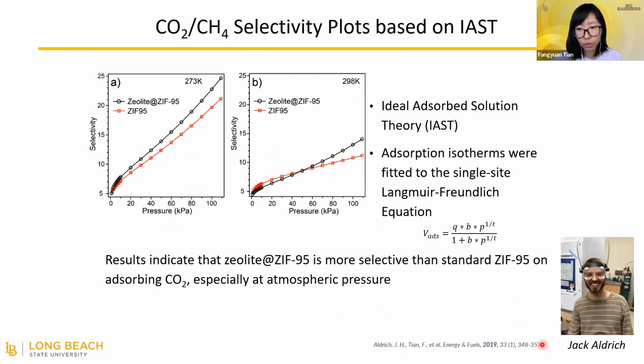Another student in my lab, Jack Aldrich, did the computational work based on the ideal adsorbed solution theory, or IAST, to figure out the selectivity of this material toward carbon dioxide and methane. And we noticed that for the hybrid material, even at room temperature, the selectivity can go up to around 16. That means for every 16 molecules of carbon dioxide trapped in the pore, only a single methane molecule could enter. So this is a pretty good selectivity. That means we can use this hybrid material to purify methane from landfill gas, even at room temperature. So it's much better compared to ZIF-95.